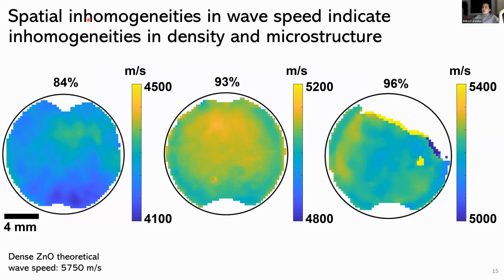And when we did that, part of it was exactly what we expected. As you increase the relative density of the bulk part, the average wave speed in the samples increased. You can see that the range here goes from 4,100 to 4,500, and then all the way up to 5,000 to 5,400. So they each have a 400 meter per second range, but that mean value is slowly increasing as we increase the relative density. Again, that is pretty expected, but there were a couple of things of note when we started looking at the ultrasonic results.